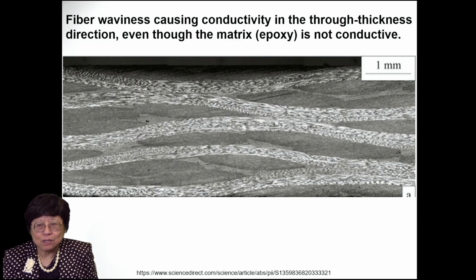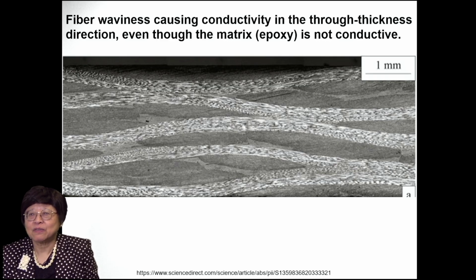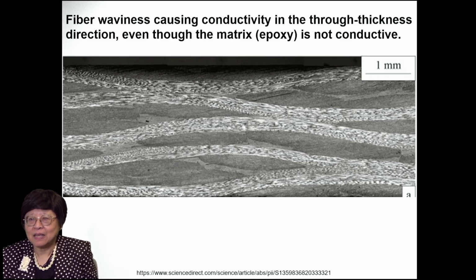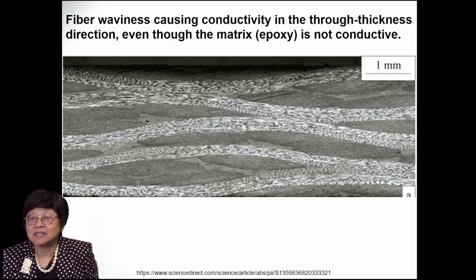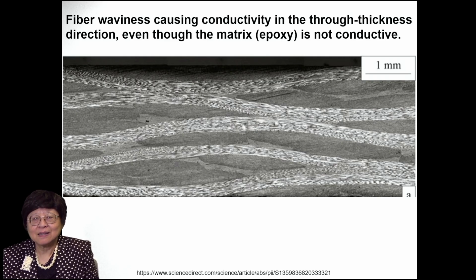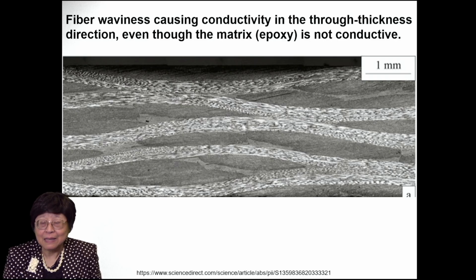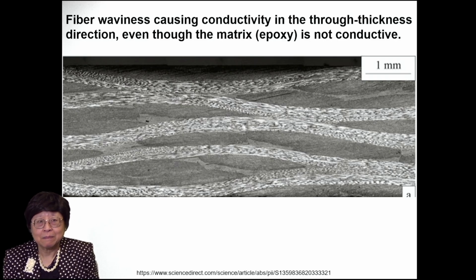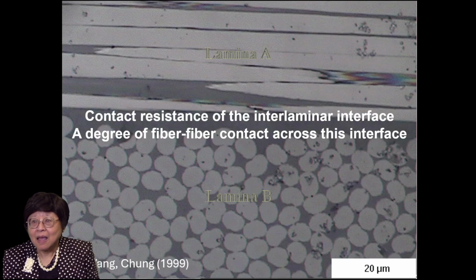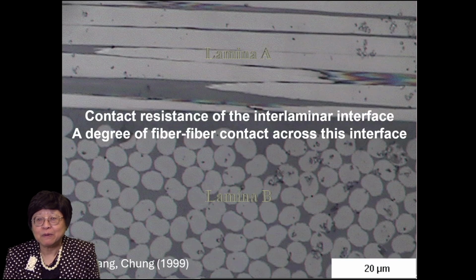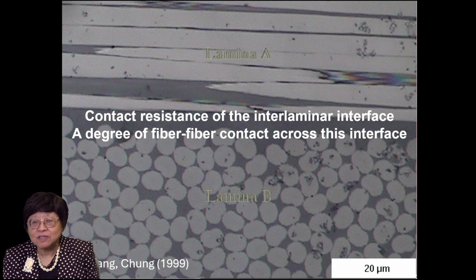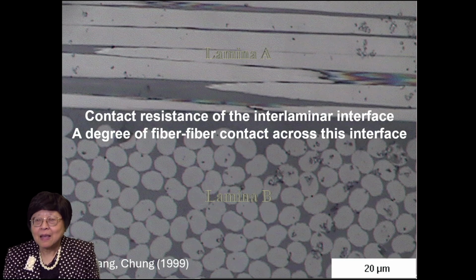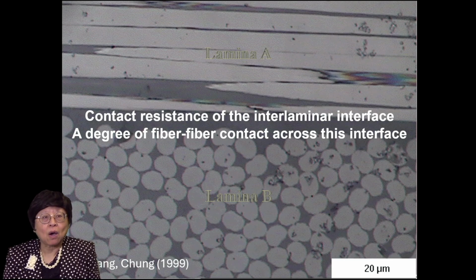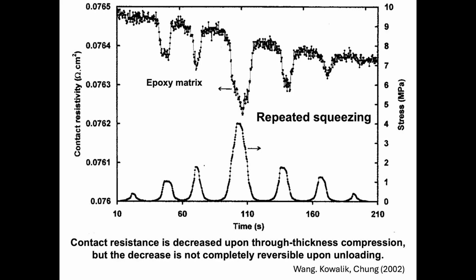Now, the carbon fibers in a composite are never perfectly straight. They're always a little bit wavy. As a result of the waviness, the conductivity in the vertical or through thickness direction is never zero, even though the matrix polymer may be insulating. Okay? And so there's always a degree of fiber-fiber contact across the interlaminar interface. And so the contact resistance of that interface is never infinity. And the contact resistance would go up upon delamination.